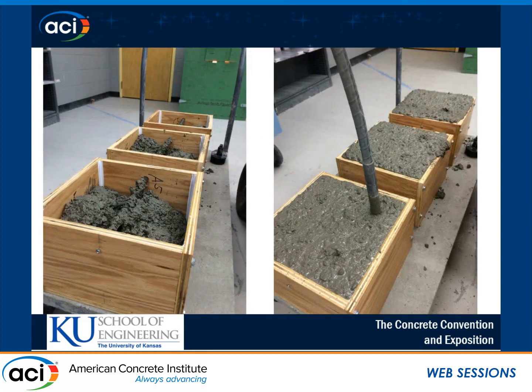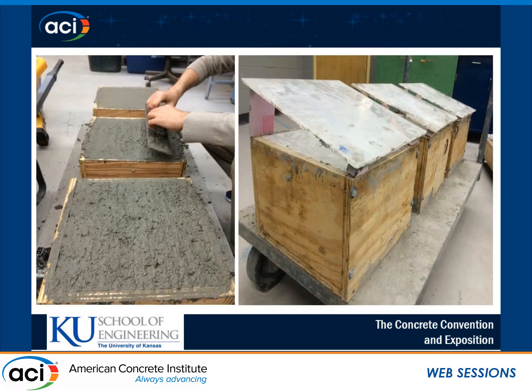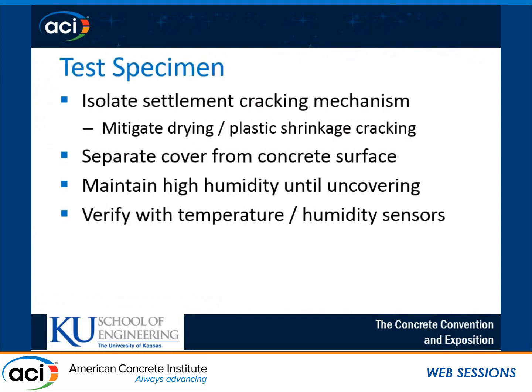And here are some pictures of the process. So there's filling and vibrating each layer, and finishing. And the figure on the right is part of our curing regime, which was one of the things that was really important in the evolution of this test procedure. One of the things we do after we finish the surface of these specimens is we place a sloped piece of plexiglass over the top.